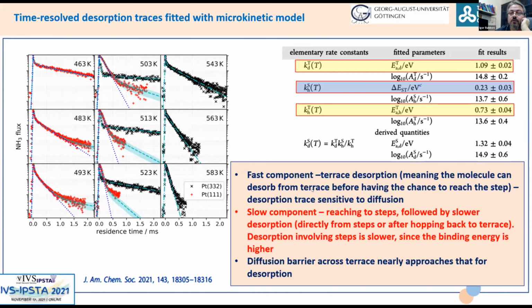Basically, what happens when the molecules are landing on these platinum-111 surfaces, where the steps are very sparse, since the distance they have to pass between the steps is actually 250 rows of platinum atoms, they can easily desorb along the way without reaching the steps. That's one thing. Now, the slow component, right? The slow component is related to the ammonia molecules that reach the steps and desorb either directly from the steps or after hopping back to the terrace, because the steps apparently are stabilized in comparison to the terraces by 0.23